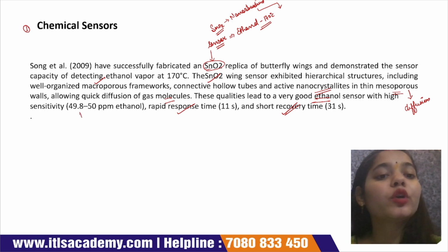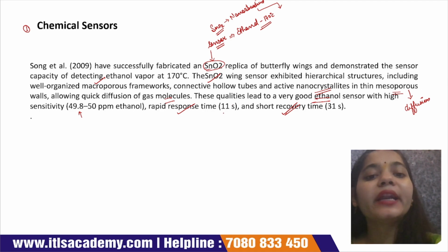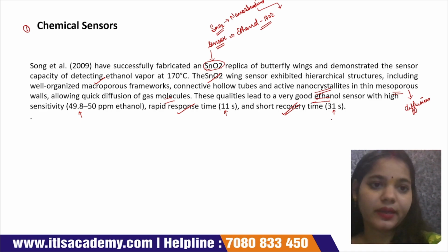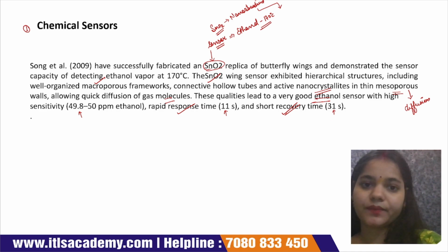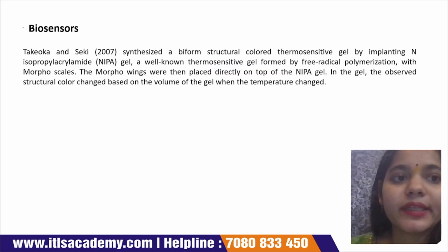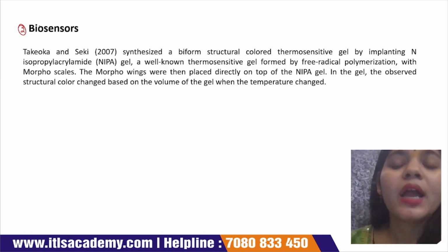Sensitivity is 49.8 at 50 ppm, response time is 11 seconds and recovery time is 31 seconds. This is a chemical sensor. Now we understand the second application, that is a biosensor.